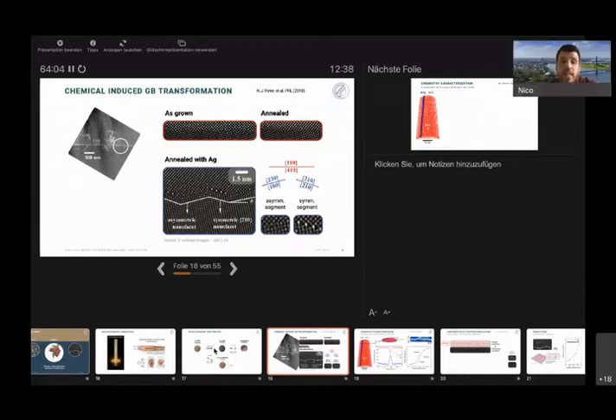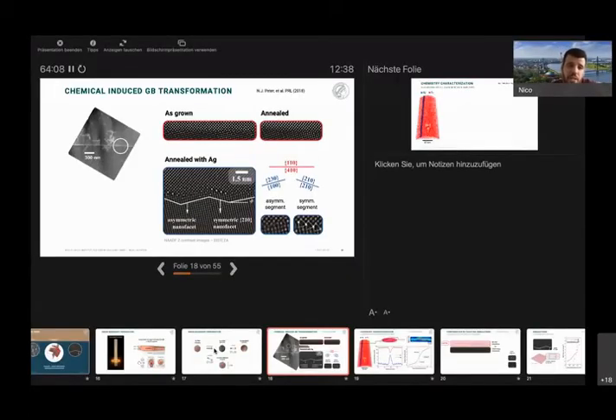Stigmation, so these are aberration corrected, yes. So this is high resolution, aberration corrected high resolution microscopy. And then also these are averaged images. So we took a set of, I think, 20 images and then averaged them. And I don't remember if for this one, I think we did a registration of the images as well to align them on top of each other.